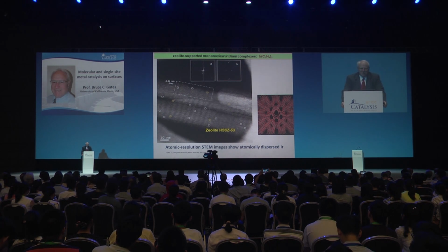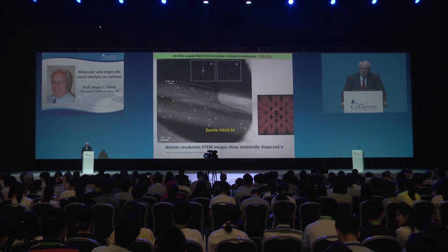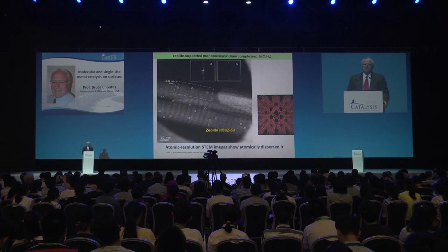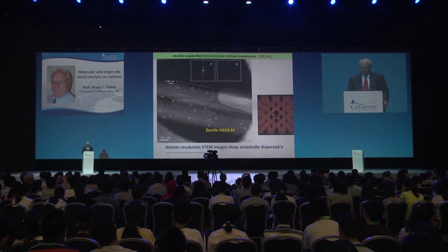What we see is that the low loading gives us essentially a random distribution of these catalytic species. So well-dispersed catalytic sites seen with the microscope.